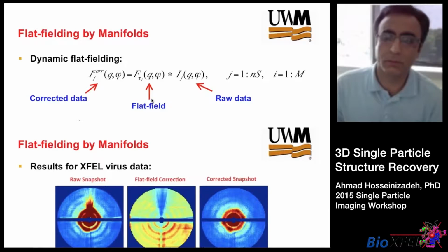Compared to which problem? For diffraction data, you can make the assumption that it should be phi invariant in the range, but if it was an image and you're correcting, I believe the same principle holds. Well, I can answer that. Actually, it is not easier because their cameras are already flat-field corrected prior to the experiment. Further, the dynamic range is extremely small compared to the XFEL, so you don't have this non-linearity issue. Also, you can measure the background statistics essentially from a uniform illumination.